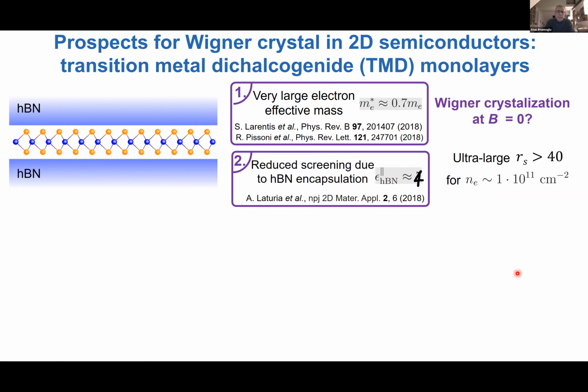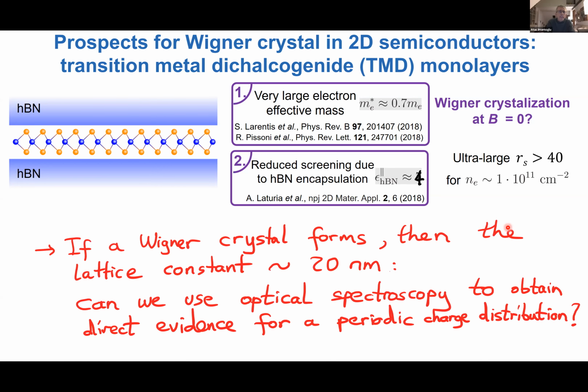So now the new materials in the game are these two-dimensional semiconductors. I briefly mentioned them. What is characteristic here is that the effective mass can be large, the dielectric screening is reduced, and when we put these together, we find that the rs parameter can actually exceed 40 for similar densities. So the natural question is, if a Wigner crystal forms at, say, zero magnetic field, how do we detect its existence? In particular, can we obtain direct evidence, say using optical spectroscopy, for the periodic charge distribution? If you look at the numbers, a lattice constant of 20 nanometers and optical wavelengths around 800 nanometers doesn't look very promising, but I will try to convince you that by using excitons, this is indeed possible.